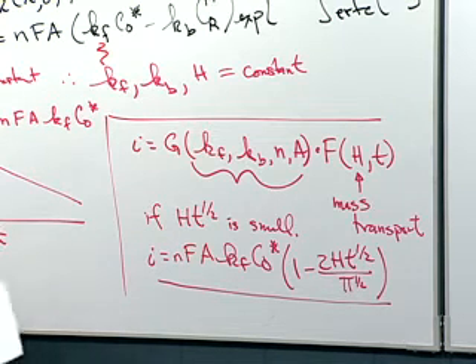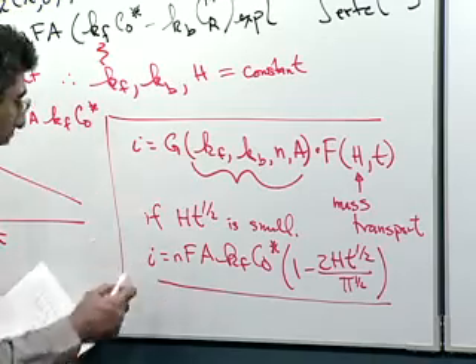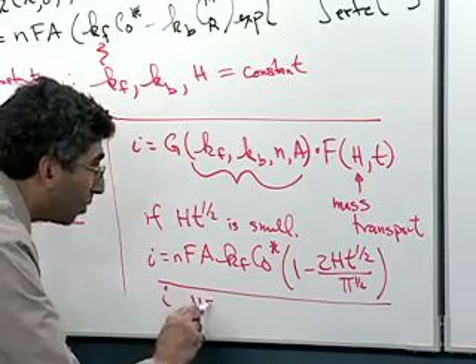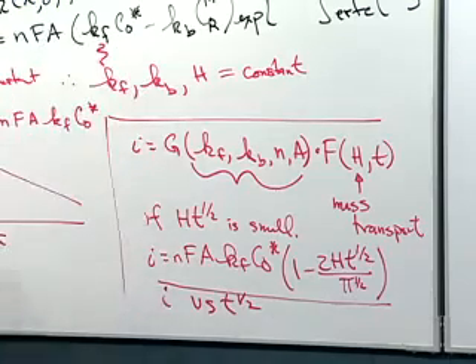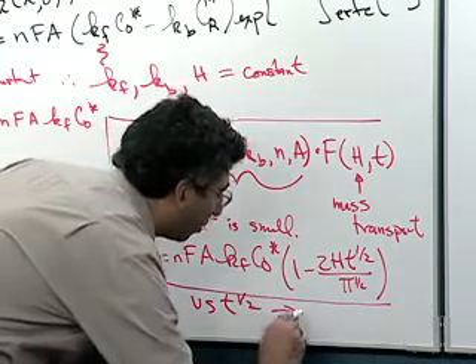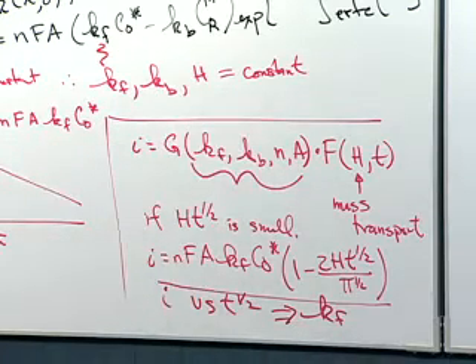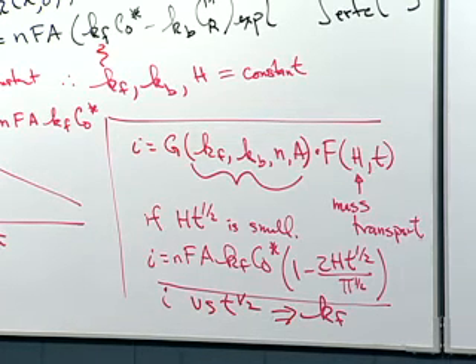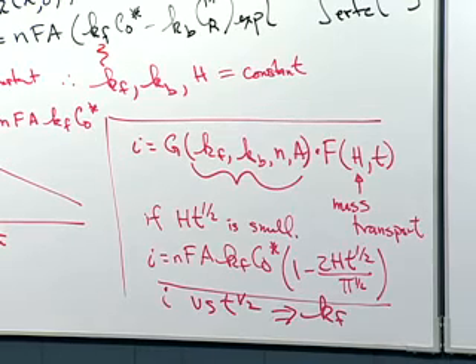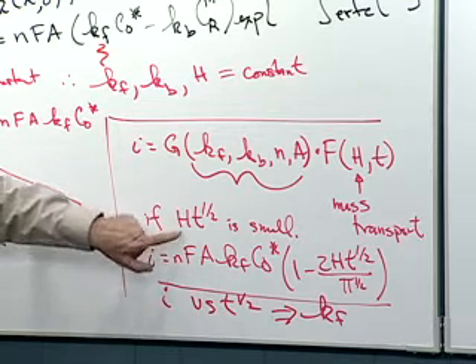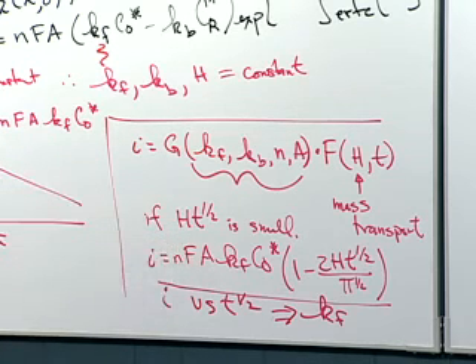And then you see, if I make a plot now of i versus t to the 1/2, then I predict a linear plot, and out of the intercept, I can extract the value of kf. And of course, I'd have to do that for several different potentials now, because kf is potential dependent, and I need to get that piece of information. Okay, so from this approach, I have the opportunity, when my rate constants are in the right regime, so I can control h, of extracting the rate constant.